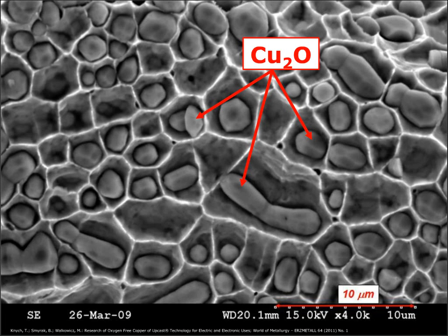The copper oxides influence the processing performance of such wire rod. In other words, this type of wire rod is hard to process into very thin wires in the range lower than, let's say, 100 micrometers, since the size of copper oxides in the microstructure of such wire rod can reach even 10 micrometers, like in the picture you see.